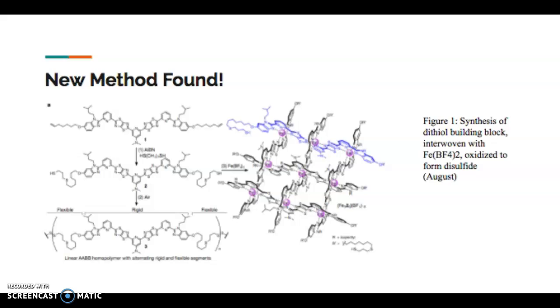And these blocks were interwoven via metal ions, specifically iron ions, into a grid structure with BF4- anions encapsulated within each of the little squares, as you can see. And the grids had ligand strands that were parallel or orthogonal, which is at right angles, to the other strands in the same layer. The grid was merely an intermediate in the synthesis of the molecular knot that was formed because the metal ions encouraged strand crossing.